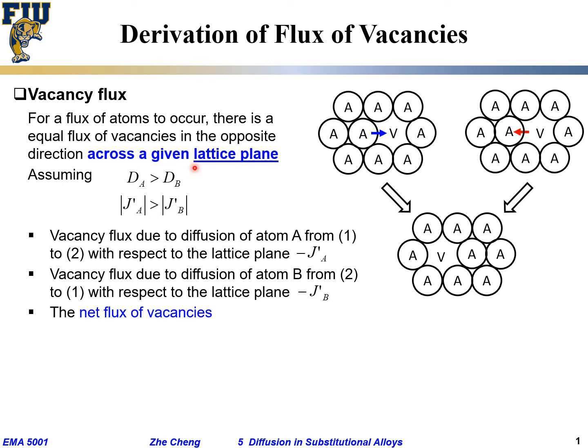They have both A atom and B atom, and we said okay, they are different. They are so-called intrinsic diffusion coefficient. dA is greater than dB. Copper is different from zinc. Zinc may have higher diffusion coefficient than copper, and JA prime would be larger than JB prime. I put absolute value because JA and D are related by the concentration gradient, but that concentration gradient is the same value for A and B. For absolute value is the same.